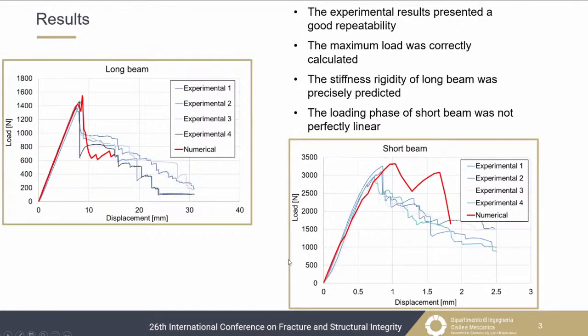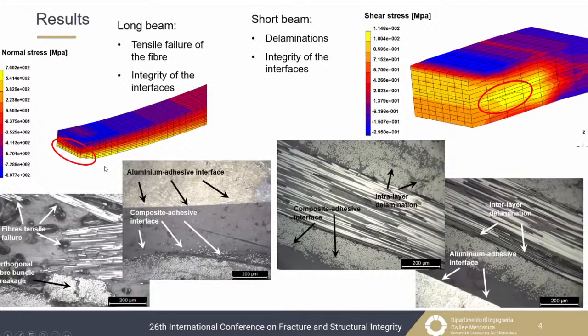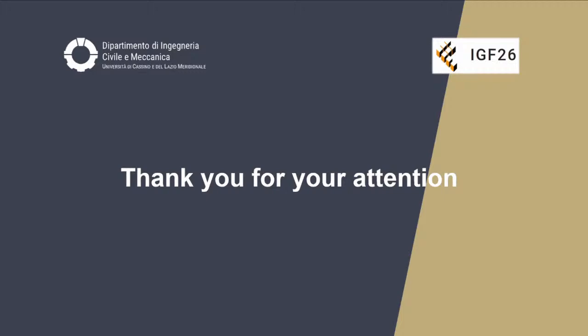As concerns the results, we can see that the numerical results are good, and they replicate the experimental results, both for the long beam and the short beam. Also, the locus of fracture was predicted in a quite good manner, as we can see from this image and from the micrographs that were taken on the failed specimens. So thank you for your kind attention.